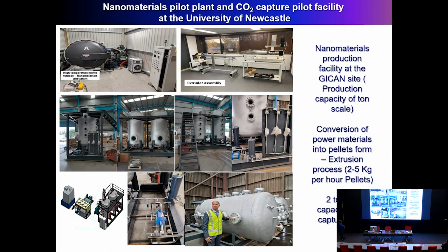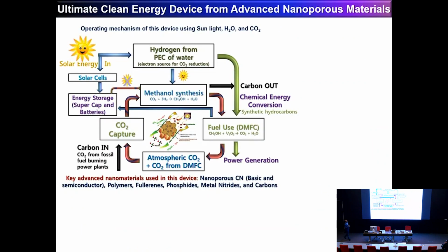And also we made a carbon capture plant with a 2-ton capacity, going from the 1 gram scale to almost a 2-ton scale. This was designed and developed by us, with oxygen, moisture, and pressure sensors. It can be operated up to 30 bar and temperatures up to 600 degrees centigrade. And this is the first academic example of a carbon capture unit using carbon-based material, and this will be commercialized in collaboration with Indian companies. So I have demonstrated various technologies like seawater splitting and fuel cell, CO2 capture and conversion, and energy storage. That's a battery.